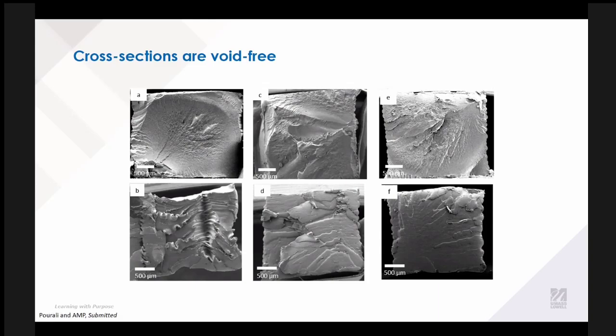So I've talked about the properties being close to that of bulk properties, and we think that a lot of that is because our cross sections are void free. So on the top, I'm showing freeze fractured SEM micrographs, and then in the bottom, we're showing fracture surfaces. And so you can see in the freeze fractured samples that there really aren't any voids, but you can see where the individual layers should be, and we've gotten such good coalescence that these are void-free structures.